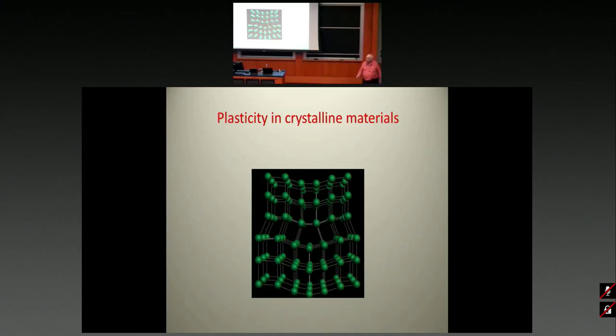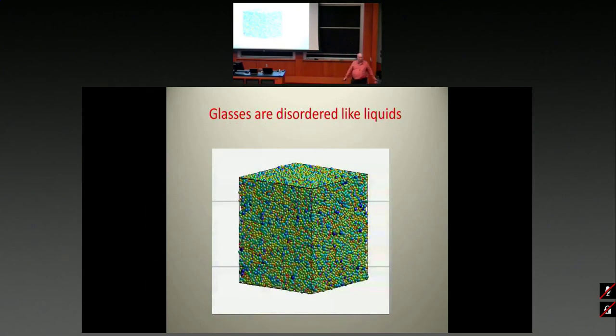So this has been already understood many years ago, and even towards the last part of the 20th century, even when you have a field of dislocations, people have made progress in understanding what is going on. But it's clear that plasticity in crystalline materials is dominated by dynamics of dislocations. If you have a glass, it doesn't have any long-range order. I remind you, you get the glass from cooling a liquid, and there's no phase transition. So the structure of the solid is amorphous as the mother liquid. So there's no long-range order, and therefore you cannot define a dislocation, because you need to have the long-range order with respect to which you can define a defect. So then you need to discuss what is plasticity in an entirely different way.